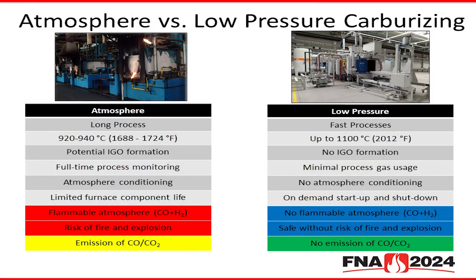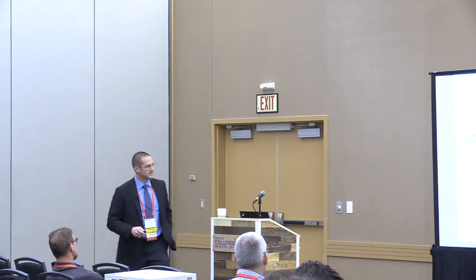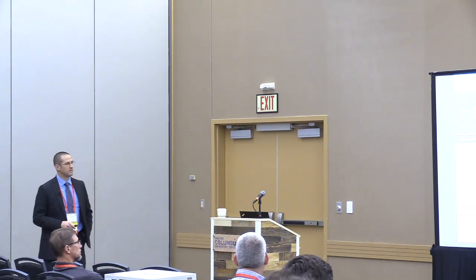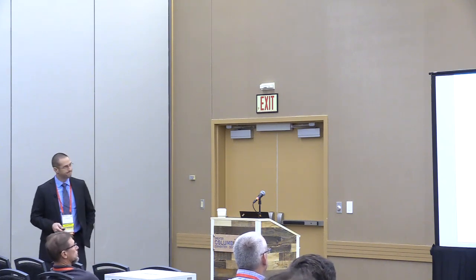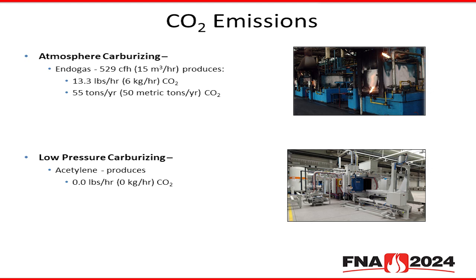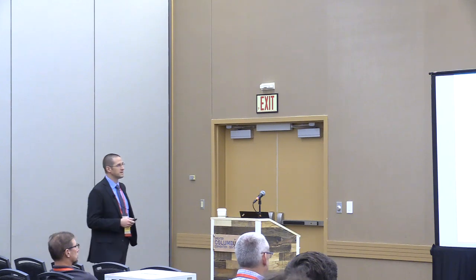But, as I alluded to, as we continue to be more and more aware of the impact of each process on the environment, this topic is very important. And in the low pressure process, there's very little, if any, emission of CO or CO2. As a comparison, if we take a typical atmosphere carburizing process as a base, before we add the ammonia to the process, just on the endogas side, we're producing, say, around 530 cubic feet an hour for the process, which leads to about 13.3 pounds an hour of CO2 produced, and that's about 55 tons per year of additional CO2 just to run the furnace.